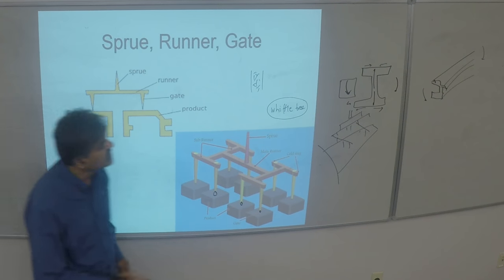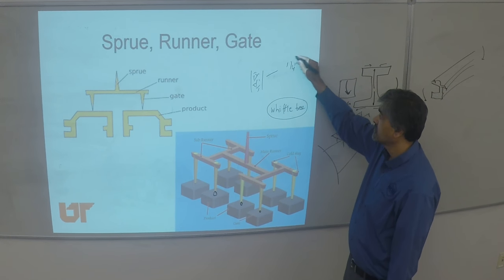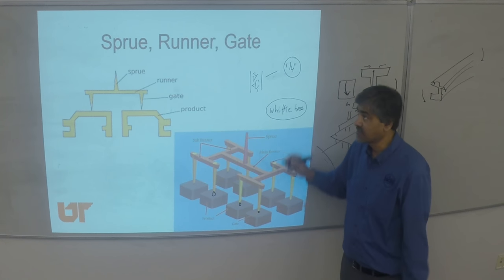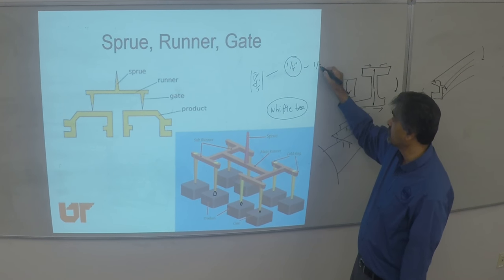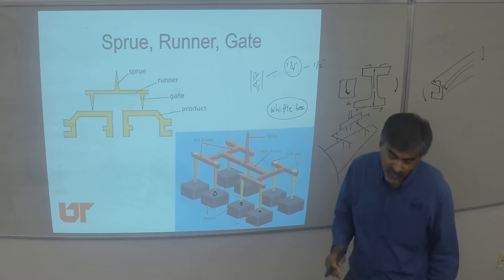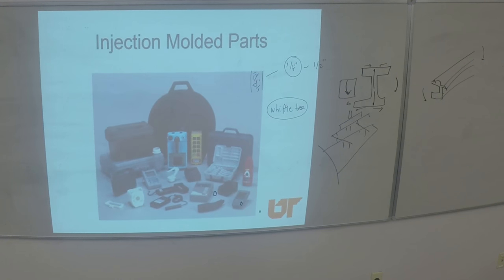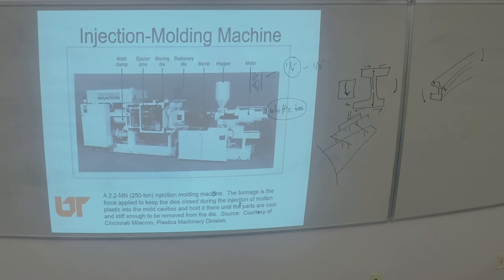There are a lot of challenges when you're trying to mold highly loaded fiber-reinforced parts. In injection molding, there's a limit of only about quarter-inch fiber length, and sometimes if you really push it, you can go up to half-inch starting fiber length. So in the screw, if you go back to what we talked about last time...